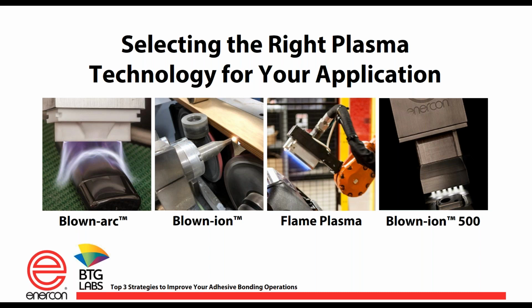The thing to keep in mind about both types of plasma is the amount of ions that are attacking the surface depends on 2 variables, and that is speed and distance. So if I want to increase the amount of ions on the surface, I need to either slow down or get a little bit closer. If I want to reduce the treatment a little bit, you can actually over-treat some surfaces, you might want to move a little further away or go a little faster.